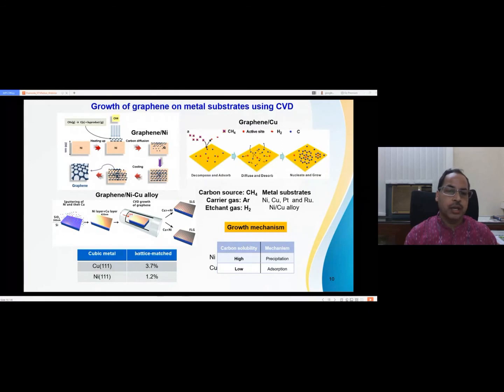Another thing is that lattice mismatch is very important. Whatever substrate you want to use should be lattice matched with carbon. Here in the copper case, copper 111 has a 3.7 lattice mismatch, and nickel 111 is 1.2. So the lattice mismatch is very small, so that graphene can grow on it.